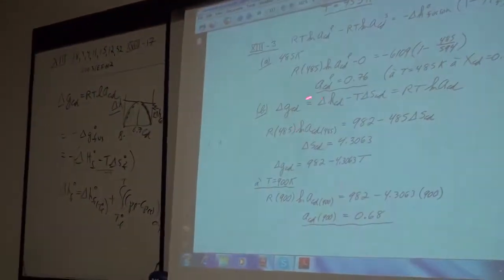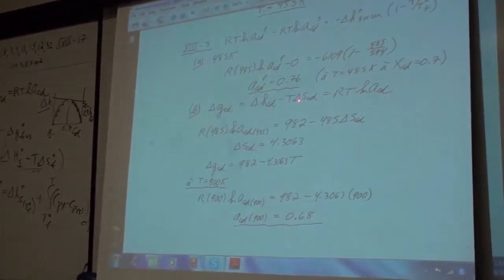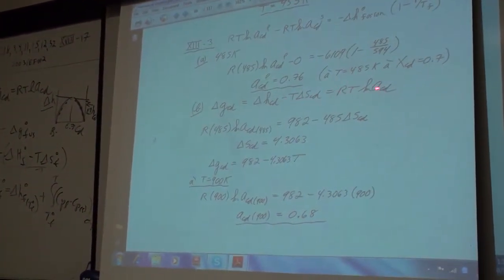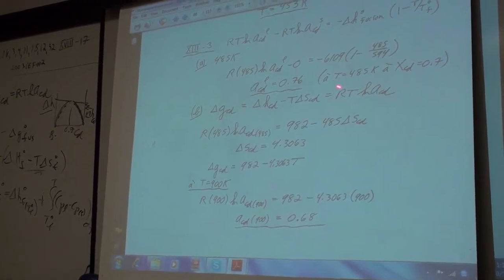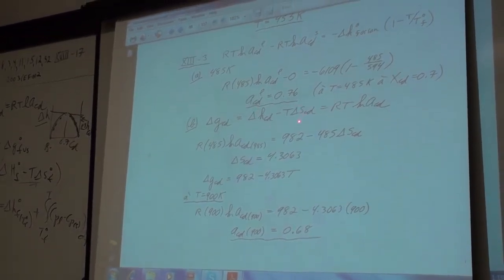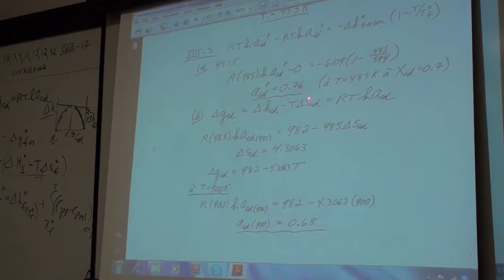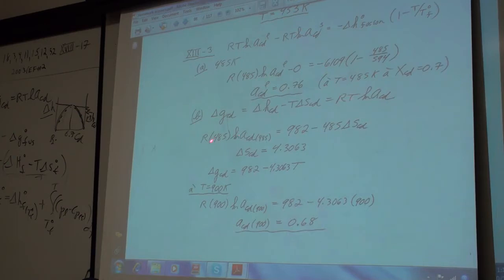Okay. So I now have the delta G at one temperature. If I want to extrapolate to other temperatures, I need delta H and delta S partial of cadmium. I can get one, I need one. So I have the partial heat of mixing of cadmium. At 485, I know the activity of cadmium, so now I can work out what the partial entropy was as well.